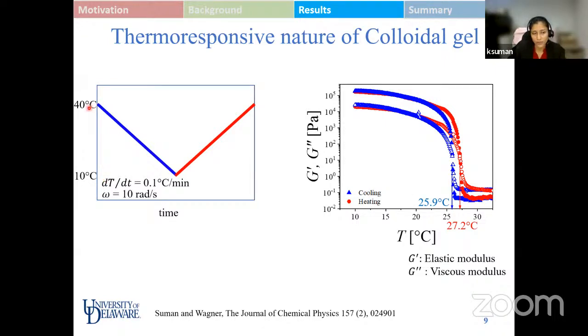As we decrease the temperature and follow the cooling cycle, the blue one, we have the evolution of G prime and G double prime shown on the right graph. The blue one is during the cooling cycle, when we decrease the temperature, followed by the heating cycle, the red one, which is an increase in temperature. Since it is liquid-like at very high temperature, it is shown by the very low value of the modulus over here. As it undergoes the liquid to soft solid transition, both the moduli intersect at a certain point and then increase rapidly by 5 orders of magnitude to a very high value.